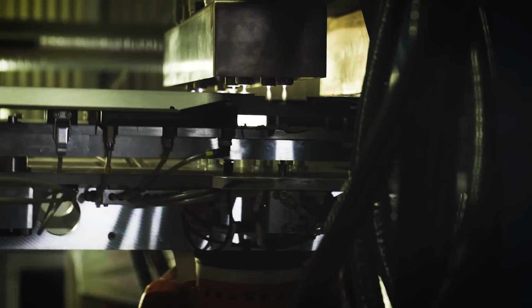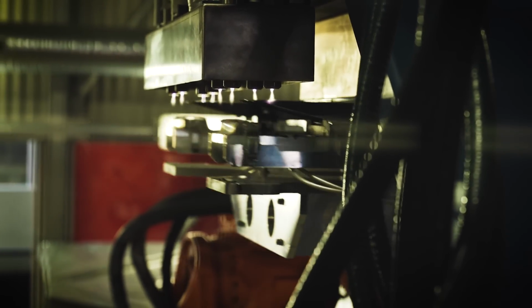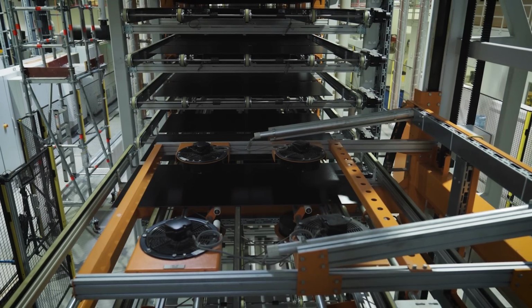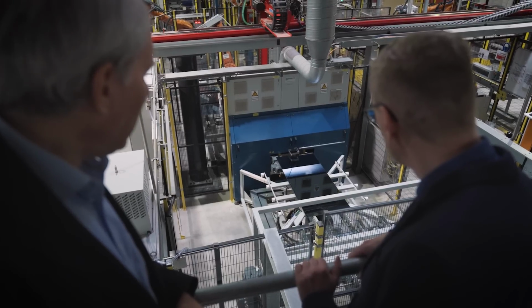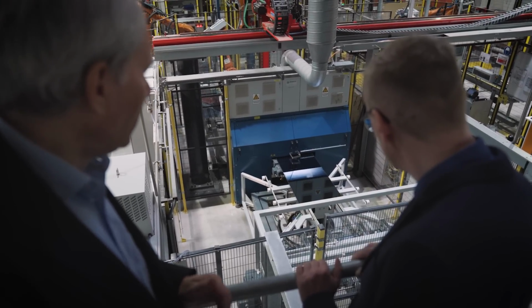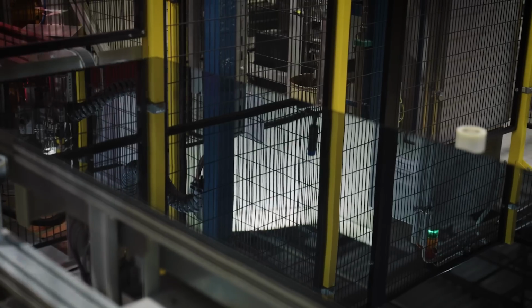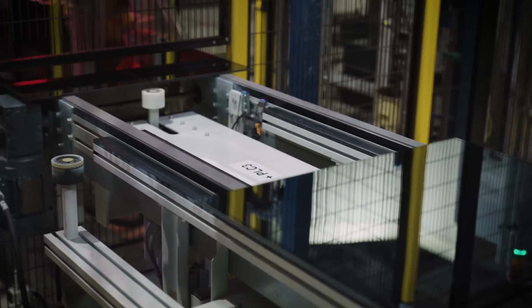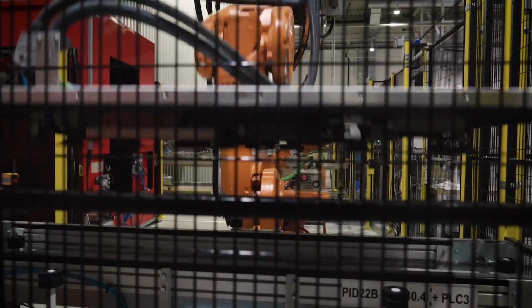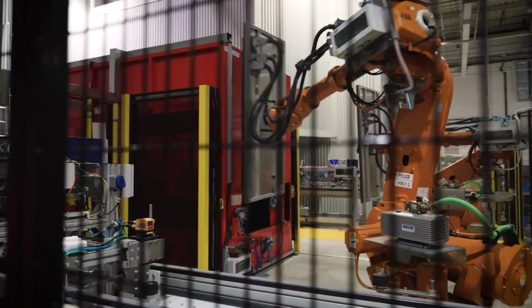And recently we reached an efficiency level close to 20% on our mid-sized modules. And this was achieved with a completely cadmium-free technology. This is a unique technology we developed. It's a dry process. This makes cost-efficient production possible, and it's also more environmentally friendly. Besides power improvements, this is a big topic for us: to develop technologies which are environmentally friendly and allow us to go for green PV technology.